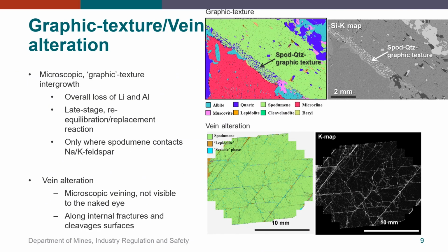Here we look at the graphic texture and vein alteration styles. In the top images, the graphic alteration involves the development of a microscopic graphic textured quartz-spodumene intergrowth, where spodumene is in contact with feldspar, mainly as albite, but in this case here with K-feldspar. The top false color mineral map and silica distribution map clearly show the graphic textured alteration along the grain margin of spodumene in contact with feldspar. Alteration results in the overall loss of aluminium and lithium and is interpreted as a re-equilibration or replacement reaction in the later stages of cooling of the pegmatite.